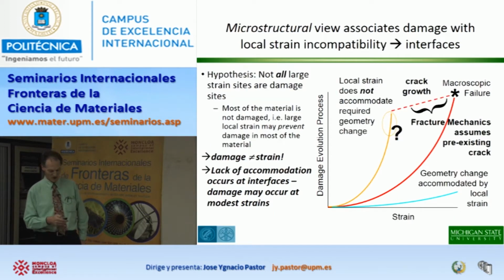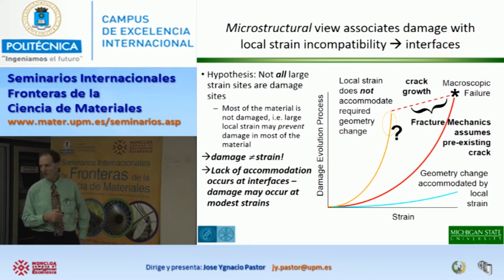However, if we look at a microstructural point of view, we tend to associate damage with local strain incompatibility, which basically means interfaces, such as grain boundaries or phase boundaries. And so it's a little more complicated. In fact, I want to pose this hypothesis, which is not typical, that not all large strain sites are damage sites. And in fact, most of them are not. So here's my thought experiment.